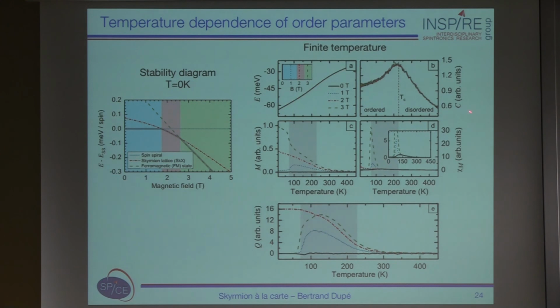If you look at the susceptibility or the heat capacity, you see that you have a peak here, which corresponds to the critical temperature, and you can define a boundary between a disordered and the ordered phase. This allows us to set up these bars here. From this gray shaded area, we use it to define the right side.